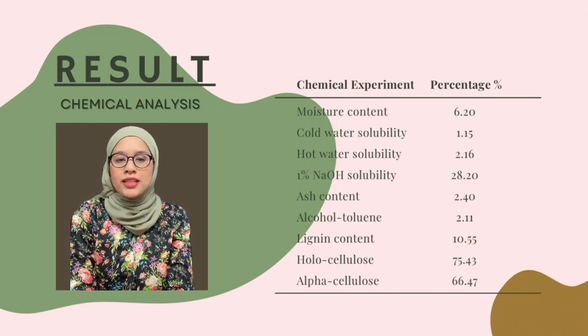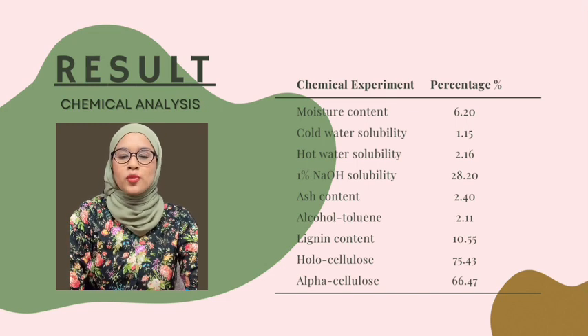And then Kenaf Bast has 2.11% of solubility in alcohol toluene, 10.55% of lignin content, 75.43% of holocellulose, and 66.47% of alpha cellulose. Kenaf's Bast has low lignin content, high holocellulose and alpha cellulose, which gives it strength and makes it a good material for paper pulp. However, there is room for improvement in this experiment.